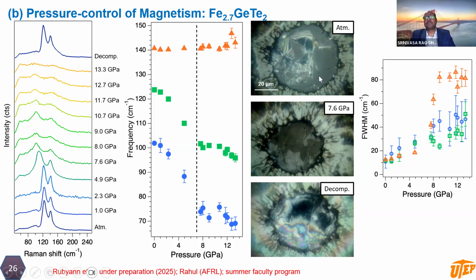So when the measurement was taken at atmospheric pressure, you see the optical image of the crystal, and upon applying a pressure of about 7.6 gigapascal, you see the optical image changes, and upon decompressing the cell, we started getting the crystal back to normal. So it means that one can use pressure as a tuning knob to control and manipulate the magnetic properties of these materials. Our theory group is doing some calculations on this part. Very soon, hopefully, we will complete these measurements and submit for publication.